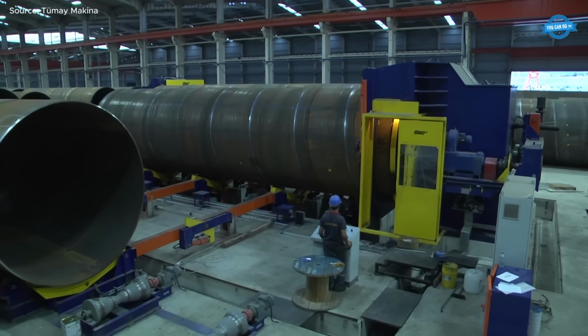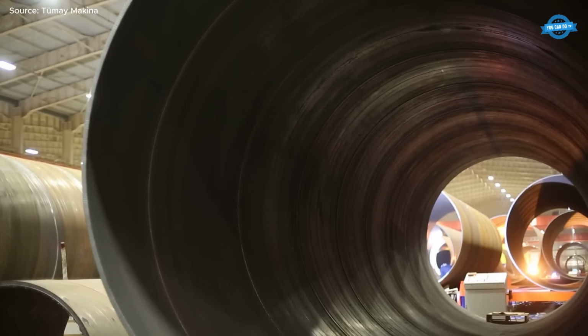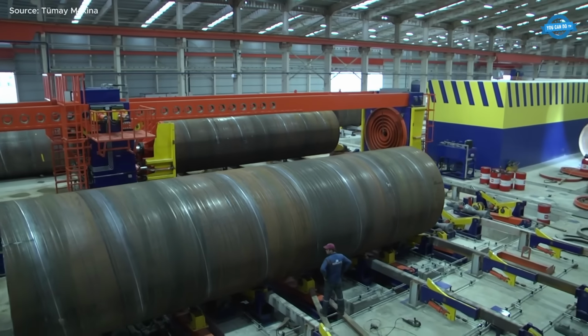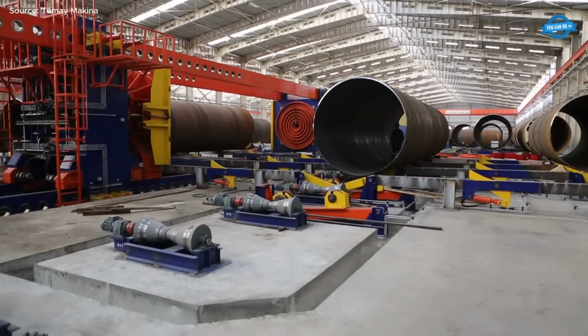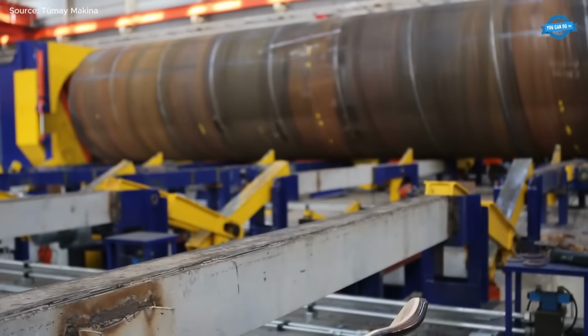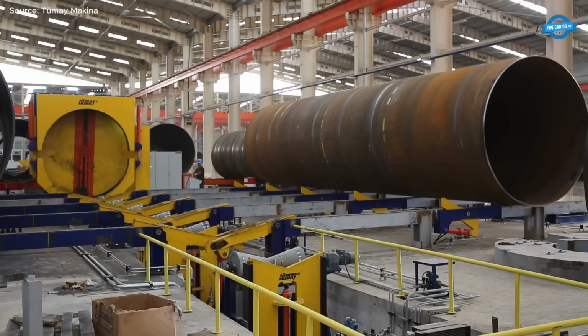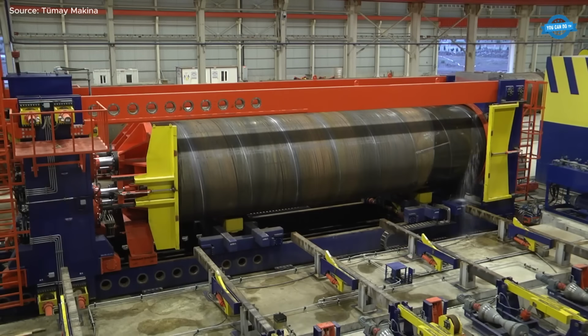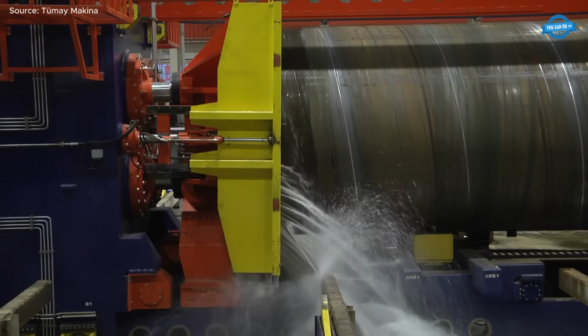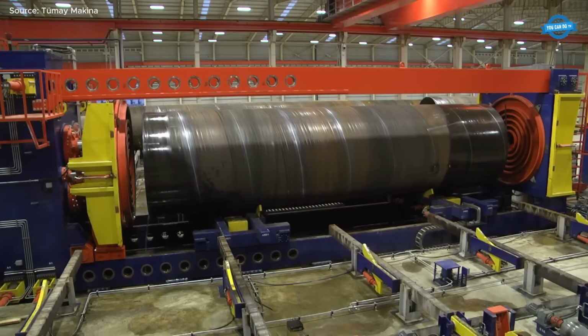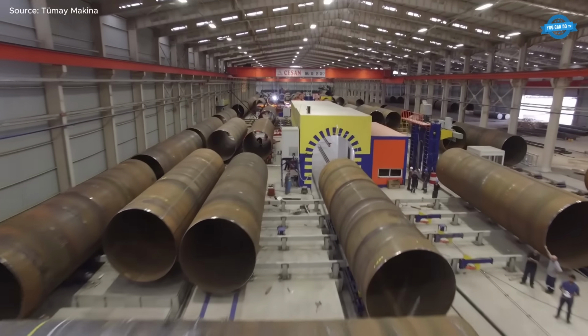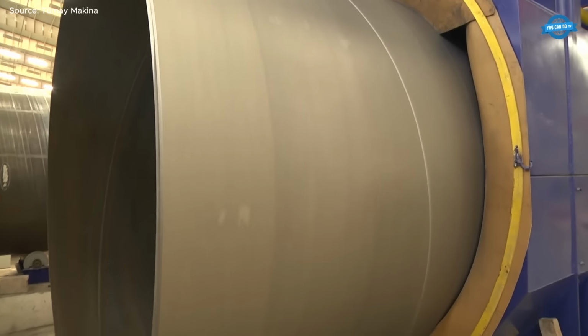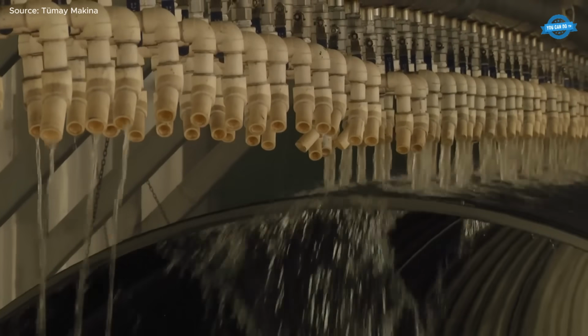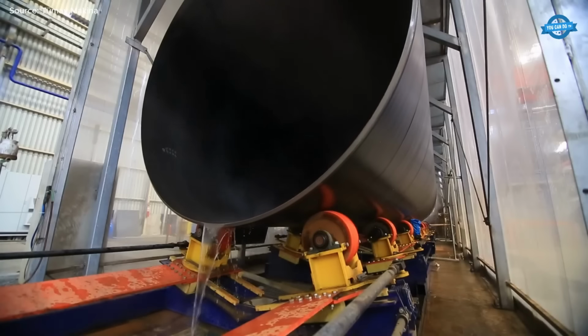Quality assurance is critical in pipeline manufacturing. Hydrostatic testing machines inject pressurized water into each pipe to confirm leak resistance, while real-time radiographic inspection systems detect hidden weld defects. The production line can also integrate coating technologies capable of applying epoxy, polyurethane, or polypropylene layers for corrosion protection.